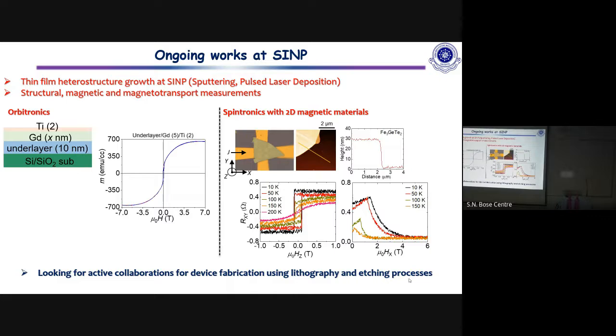So this signature, when you apply the magnetic field in the plane and you measure the transverse resistance, we previously showed that if this is a Stoner-Wohlfarth magnet, then it should not show this kind of behavior. But here what happens is it goes up and shows this peak and then comes down. And we showed previously that this is a signature of the existence of this spin texture in the system. Y-axis Rxy, yeah, these two are the same axis. But here the magnetic field is out of the plane, and here the magnetic field is in. And in our previous work, we also compared this data with the magneto-optical imaging.